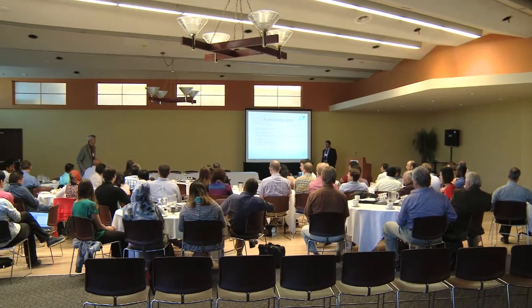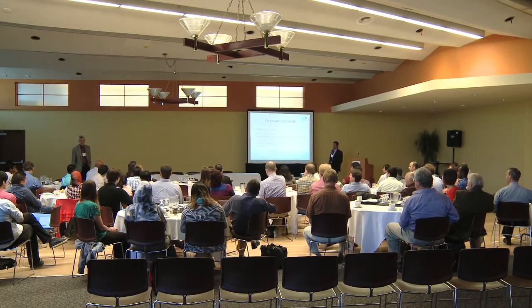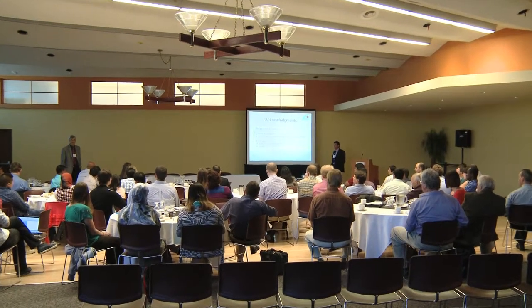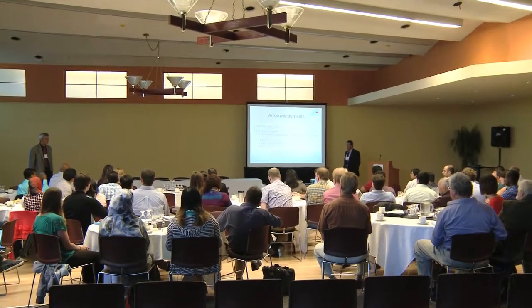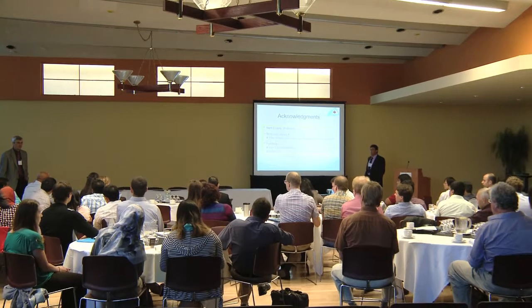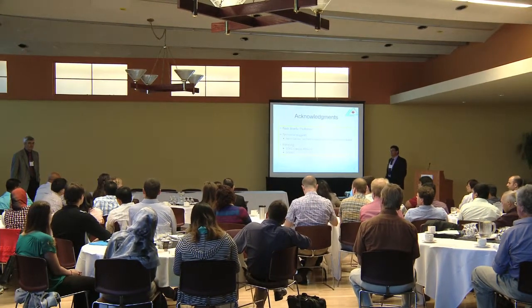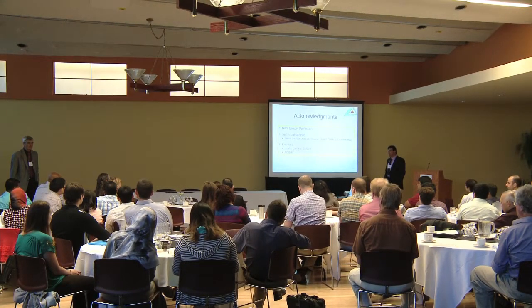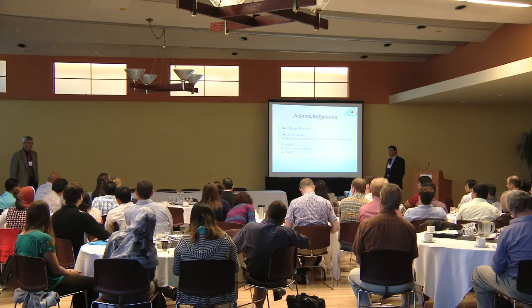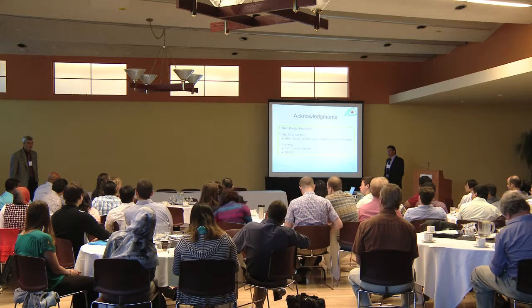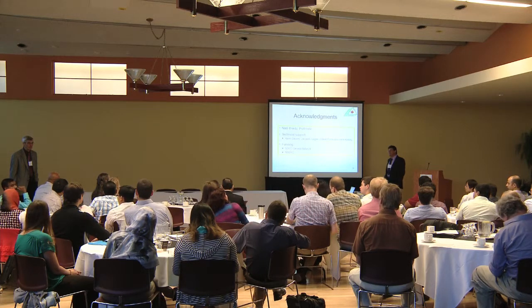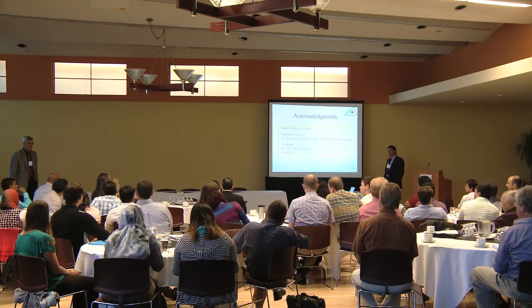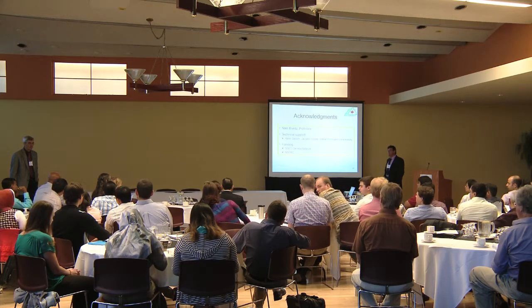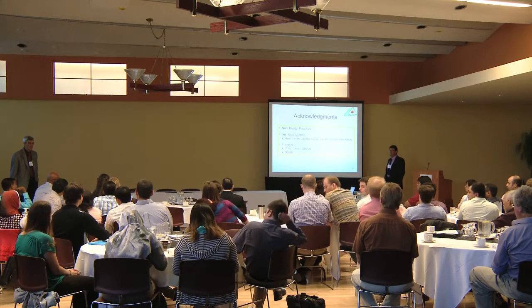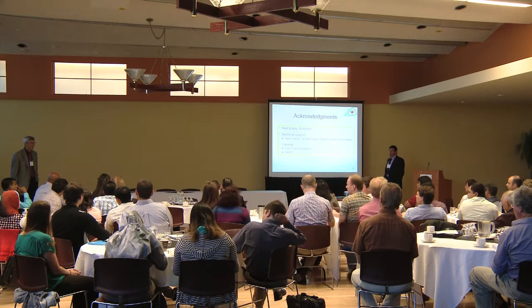One of the major challenges in dry reforming catalysis is the long-term stability of the catalyst, particularly for nickel systems. You showed about 500 minutes of data on your nickel spinel system. I was just wondering what kind of stability test information you have for longer term, at least 200 hours of data. Do you feel that it would be optimum to do that in that particular system? Any industry would like to know what kind of stability test information you have.